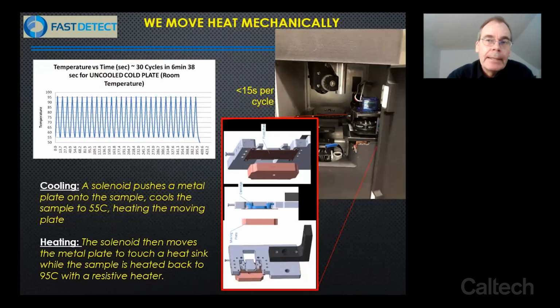And then when we heat and cool the sample, we actually do it by cold finger cooling. So instead of using a refrigeration system, we just have a cold metal hitting the bottom of the sample to cool it down from 95 degrees to 55 degrees. Then as we retract the metal, we put it onto a heat sink and mechanically move the heat. This is done with a solenoid or a relay. It's actually very simple 150-year-old technology that allows us to heat and cool.